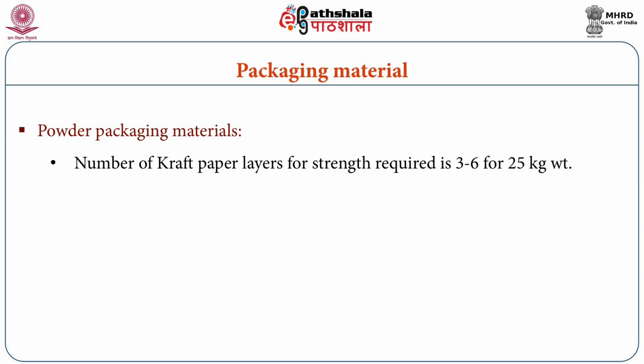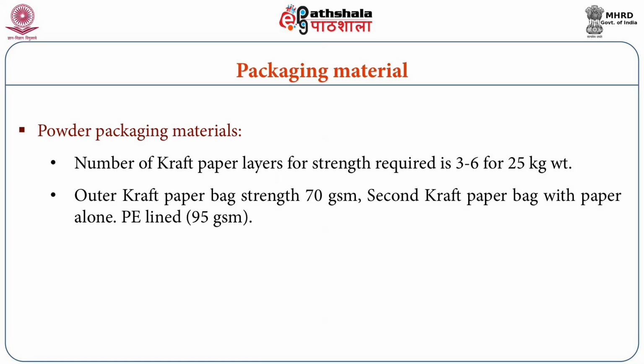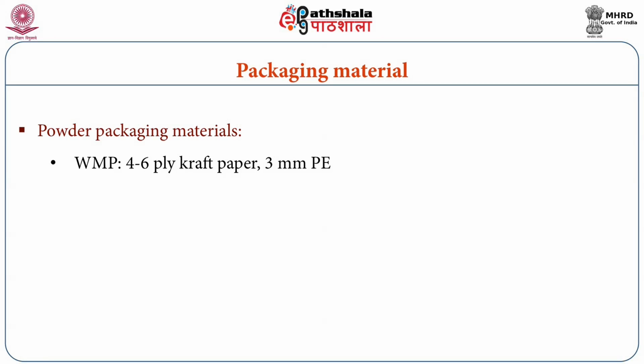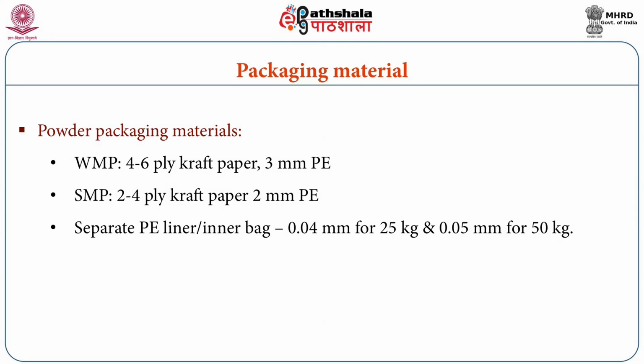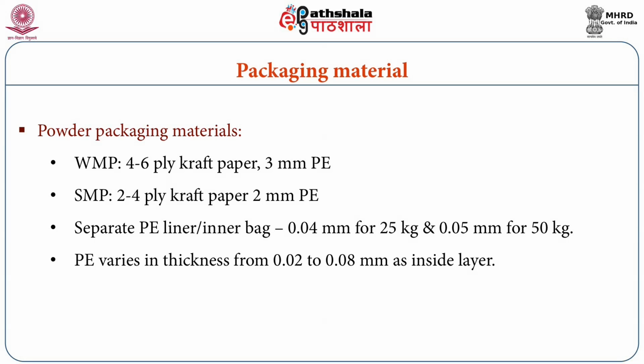The strength required is 3 to 6 ply for 25 kg weight. Outer kraft paper bag strength of 70 GSM and a second kraft paper bag with paper alone or with polyethylene lined with 95 GSM. For whole milk powder, 4 to 6 ply kraft paper and 3 mm of polyethylene is used. For skim milk powder, 2 to 4 ply kraft paper with 2 mm of polyethylene is used. A separate polyethylene liner as inner bag of 0.04 mm for 25 kg and 0.05 mm for 50 kg is used. Polyethylene varies in thickness from 0.02 to 0.08 mm as inside layer depending on the size of the bag or package.